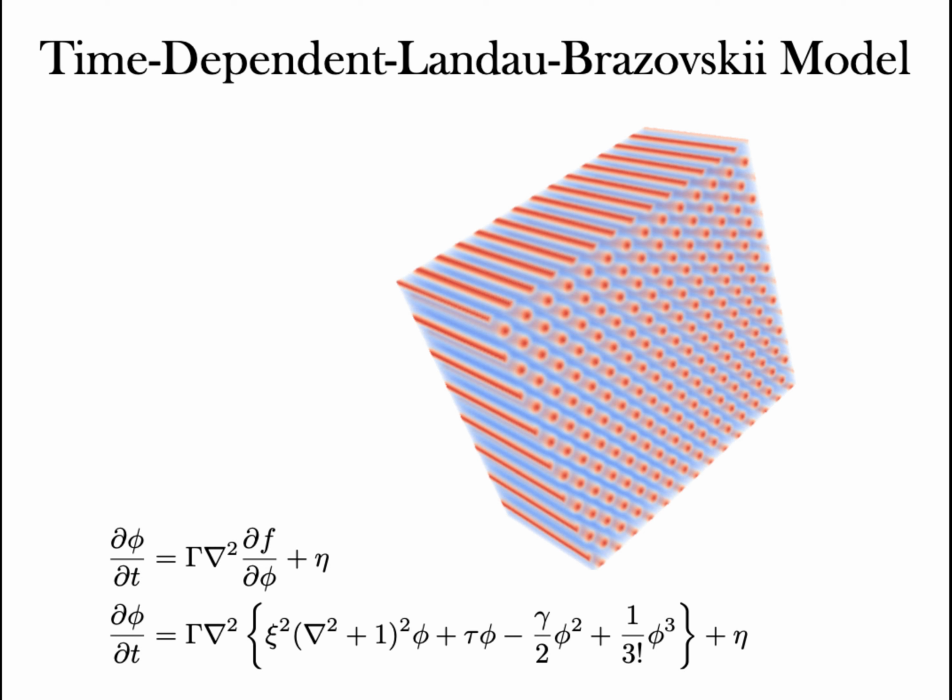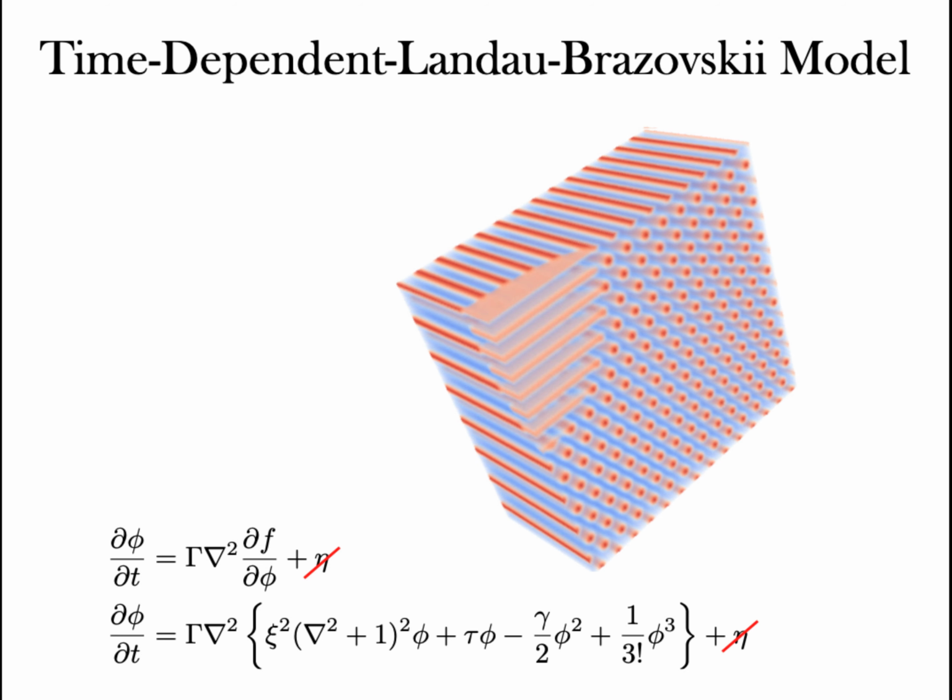We studied the evolution of the polymer melt using Model B dynamics to relate the time dependence of the composition to functional derivatives of the free energy functional. Here, eta is a noise term. It represents the compositional fluctuations. We ignore these fluctuations, effectively working in the mean field limit. Our general approach in this work is to start with a metastable cylinder phase as an initial condition, and artificially insert a droplet of the lamellar phase, and then see what happens as it evolves in time.